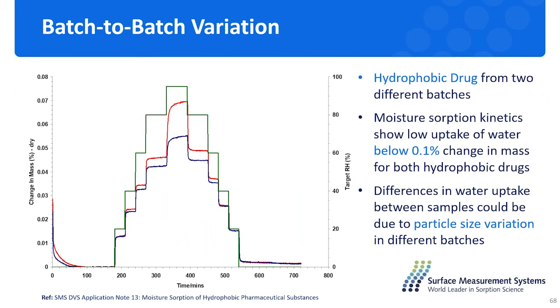And the last two applications are for the batch-to-batch variation. So DVS is a very sensitive technique that can detect the difference in the uptake for the hydrophobic drug sample, even though the uptake is very low, below 0.1%. And this difference in the uptake could probably be due to the batch-to-batch variation of different particle size from different batches. And DVS is really sensitive to detect those kinds of batch-to-batch variation.